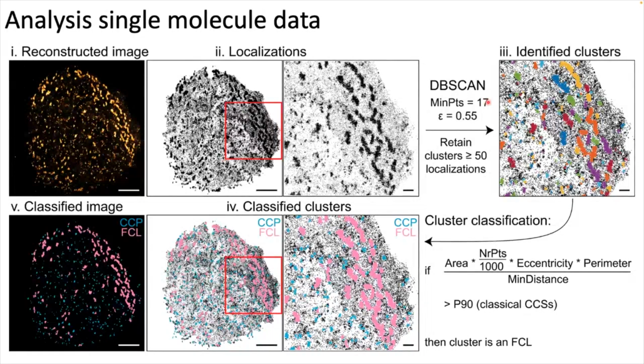How did we reach this? It was really trial and error. We first ran values between 0.3 and 0.7 and minimum points between 10 and 30. And we just looked at the image and thought, okay, would we say that this is a cluster? Yeah, I would also say that this is a cluster. This maybe, this not, okay. And then like that, we tried to do it by eye, and said, okay, this is a classification that we think is more correct, and then we set it and go with the same parameters. For some cells, maybe a different parameter would be better, but we are not going to change between cells. We just took it like that.